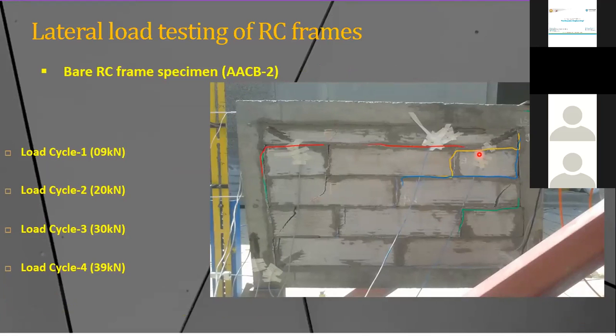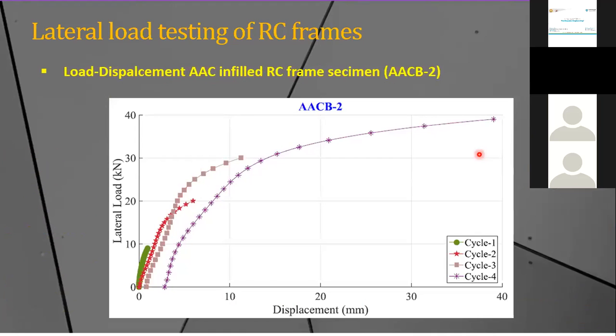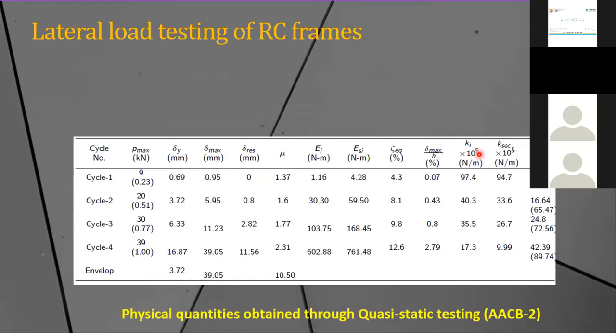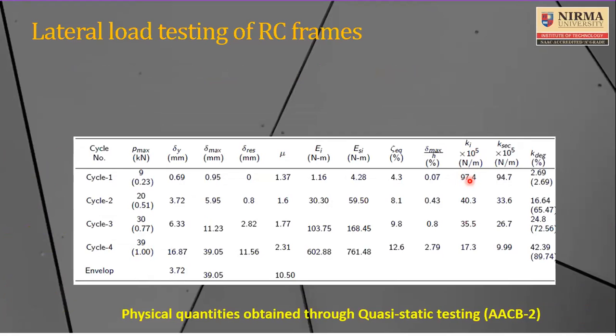We have conducted two test specimens. We prepared two specimens of AAC block and fly ash brick, and again you will see a similar pattern for the other test specimen also. Again, a load displacement plot you can see, and the result shows there is a huge improvement in the stiffness. In fact, a masonry infill provides a very good initial stiffness.